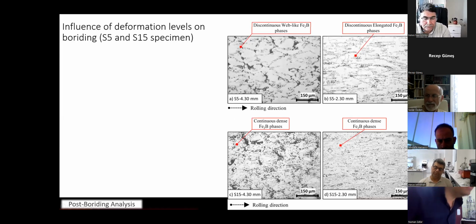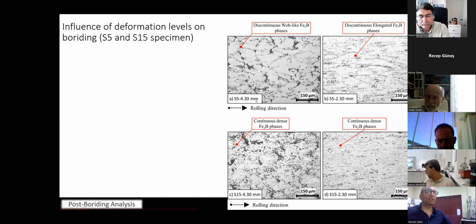Here is a material. Also, these images are taken parallel to the rolling direction. Discontinuous web-like iron boride phases are formed if you use 5% deformation ratio. And even though they are elongated again parallel to the rolling direction as the deformation level increases, because they are so small, they do not constitute an elongated fiber-like structure.